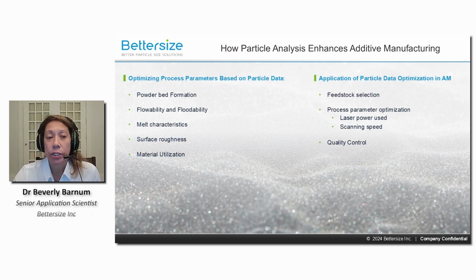By understanding the relationship between particle properties and additive manufacturing parameters, manufacturers can fine-tune parameters like laser power, layer thickness, and scanning speed to achieve better results. And this leads to fewer defects, improved mechanical properties, and enhanced surface finishes. Data on the particles, specifically their size, shape, and distribution, is crucial for optimizing additive manufacturing processes because it directly impacts the flowability, packing behavior, and ultimately the quality of the final part, allowing manufacturers to fine-tune powder feedstock properties to achieve desired outcomes like improved density, surface finish, and mechanical strength.